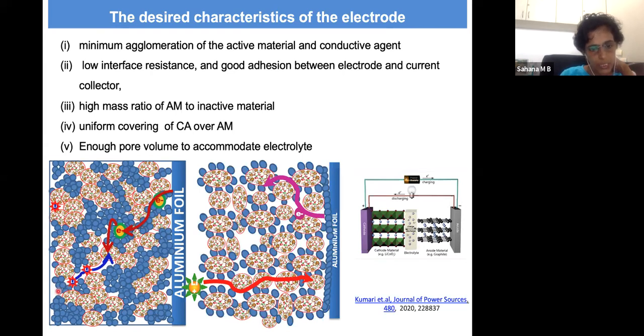Similarly, the lithium should transfer, and all these pores will be the reservoirs for electrolyte. Unless the distribution of these pores is uniform, every particle will not be involved in the charging and discharging process. Whereas in the right-hand side configuration, we have enough pores for the lithium electrolyte to go through. Similarly, the carbon black is uniformly distributed over the active material. And we also need a uniform conductive pathway for the carbon black to go from the aluminum foil to the active material. So these are the main requirements of an electrode.